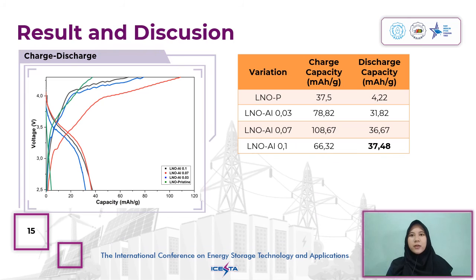The battery electrochemical performance test results are shown in the table. Discharge capacity shows an increase along with increasing aluminum component in the base material lithium nickel oxide. The capacity of the 10% mole aluminum is higher than the other lithium nickel oxide variations, according to the material characterization. A lithium nickel oxide structure with good characteristics can facilitate the lithium ion transfer process.